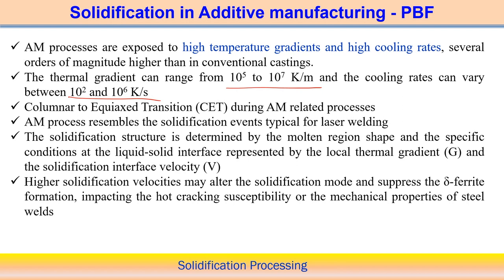Within that range, values vary depending on different techniques and parameters associated with additive manufacturing. We know that both temperature gradient and cooling rate decide the solidification morphology and mode of solidification. One important aspect is what conditions prevail when choosing different process parameters such that a transition from columnar to equiaxed structure is possible.